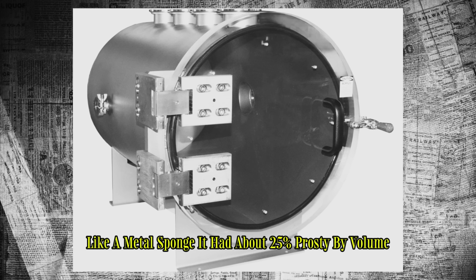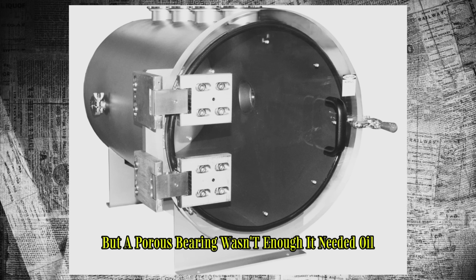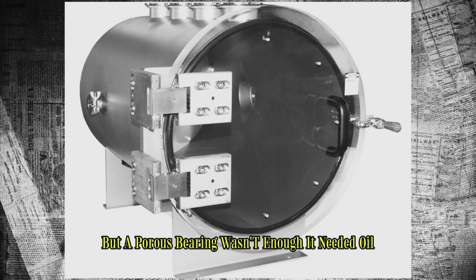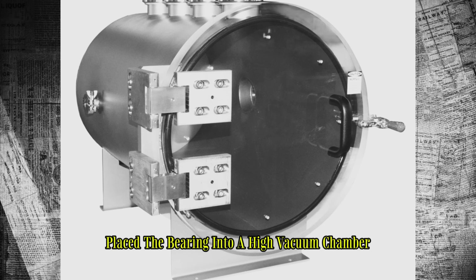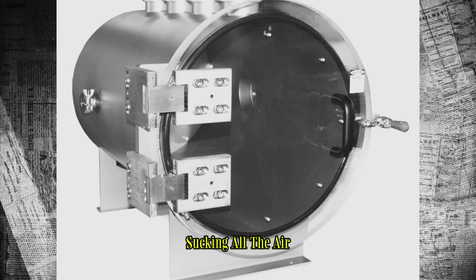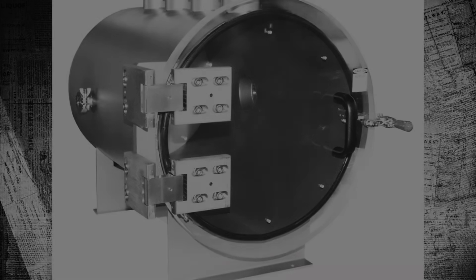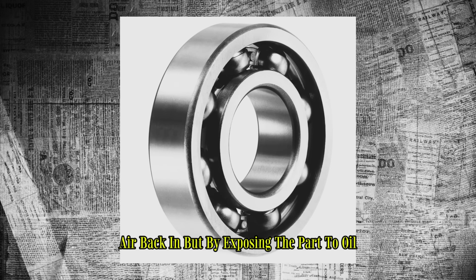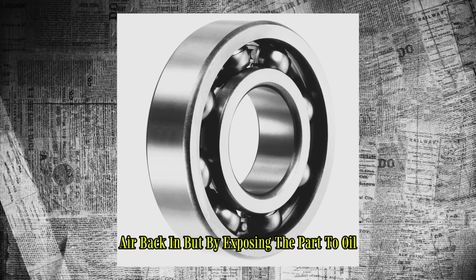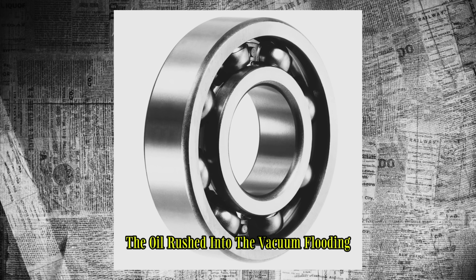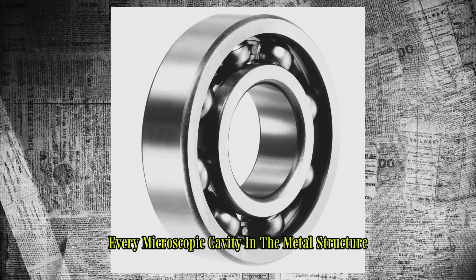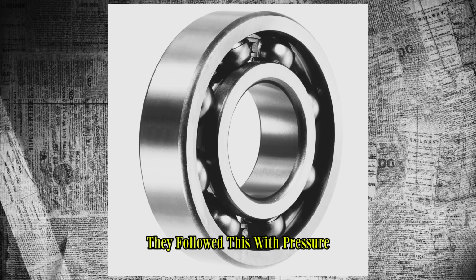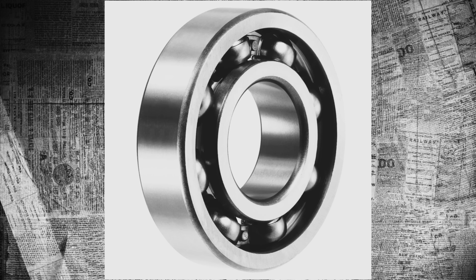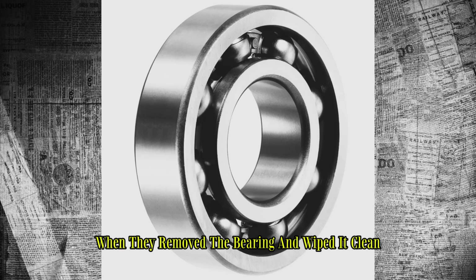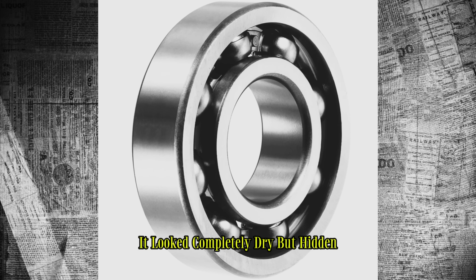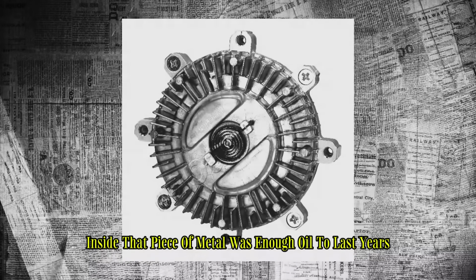It had about 25% porosity by volume, but a porous bearing wasn't enough. It needed oil. Sherwood and Calkins placed the bearing into a high vacuum chamber, sucking all the air out of the tiny pores. Then they broke the vacuum not by letting air back in, but by exposing the part to oil. The oil rushed into the vacuum, flooding every microscopic cavity in the metal structure. They followed this with pressure, forcing the oil even deeper. When they removed the bearing and wiped it clean, it looked completely dry. But hidden inside that piece of metal was enough oil to last years.